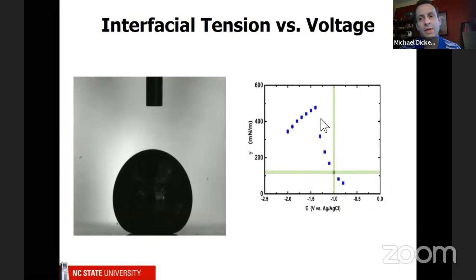Yeah, so the only two morphologies that I showed today were a sphere and a rod, but the rod was actually a crystal. It's not even liquid metal. Other groups have done really beautiful work where they've somehow sheared the metal and made it into an ellipse, less round but more rod-like. And actually, I saw just yesterday a paper where people had taken the liquid metal and put it into some pores, into a filter, and then they dissolved away the filter, and they were actually able to make nanorods out of liquid metal, which I'm still very surprised works.